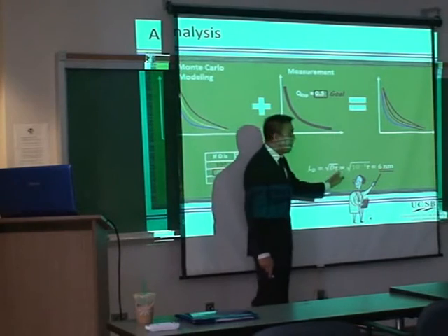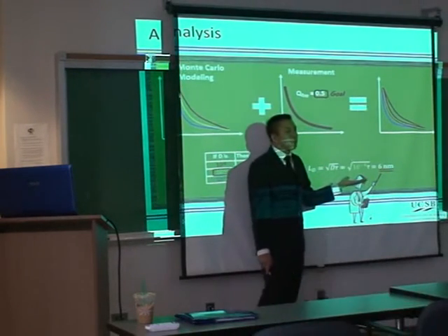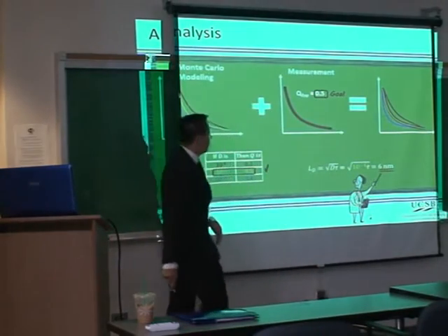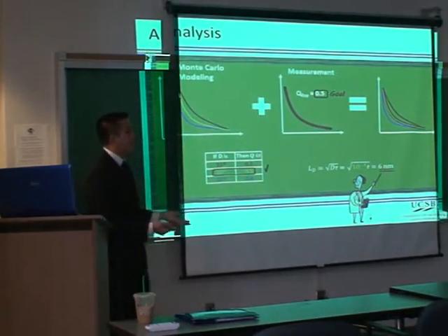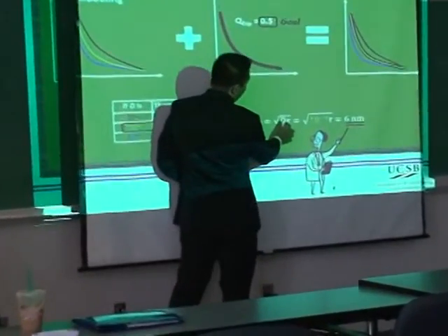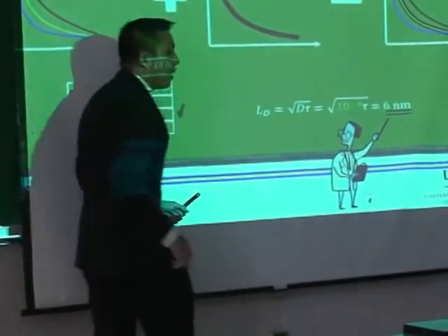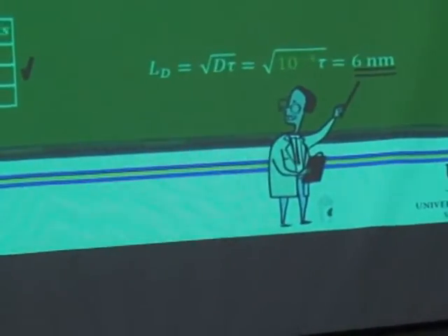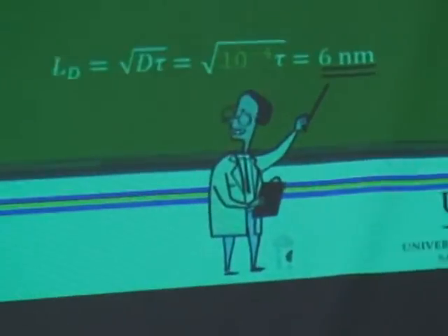You can then plug this into the simple equation for an exciton diffusion length. Here, D, and the T is the lifetime, which can be just measured from the pristine film. And finally, you can arrive at an exciton diffusion length. And this is what I meant earlier, that we're not directly measuring the exciton diffusion length, we're actually determining D, and then figuring out what LD is after that. So that's kind of the difference compared to the other technique earlier.